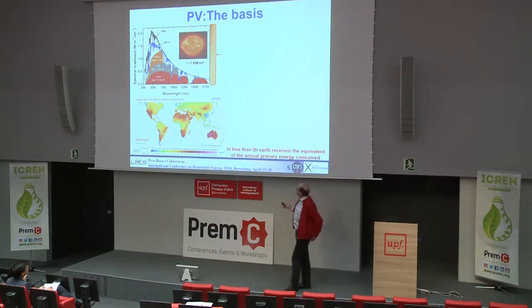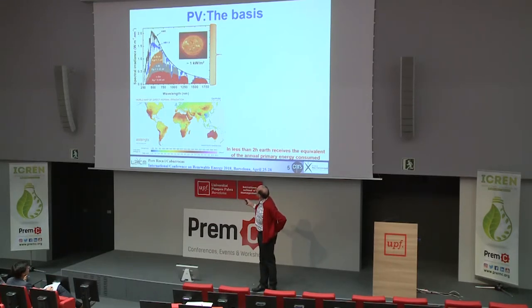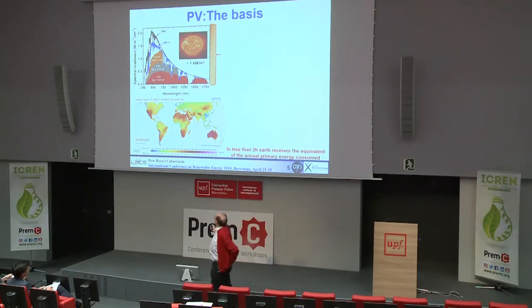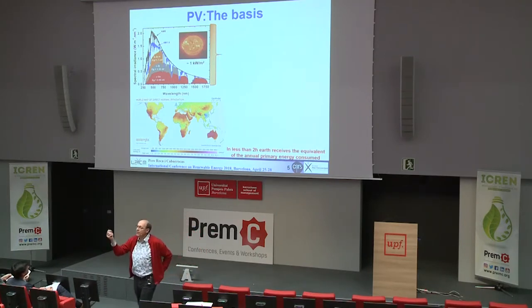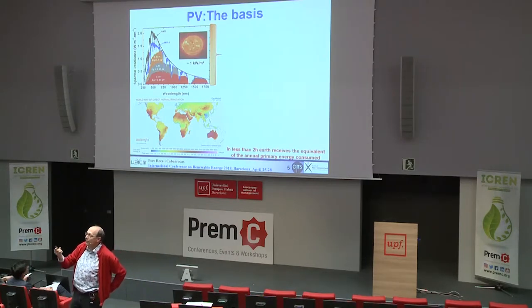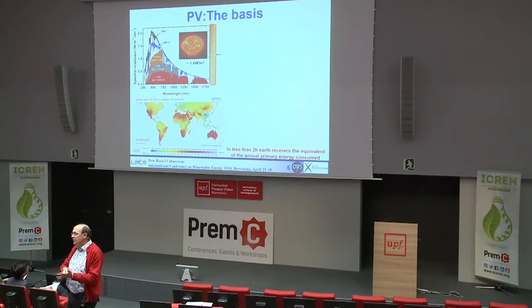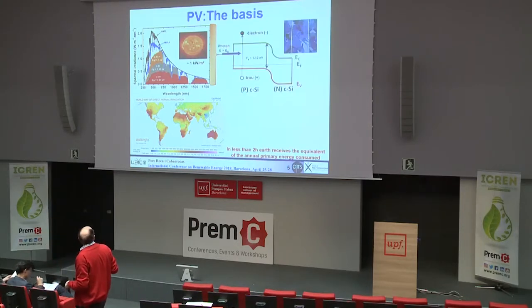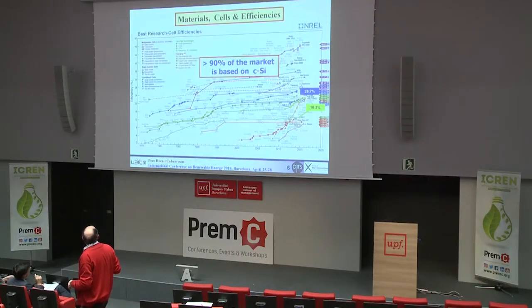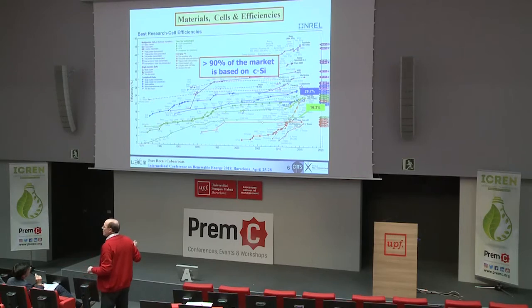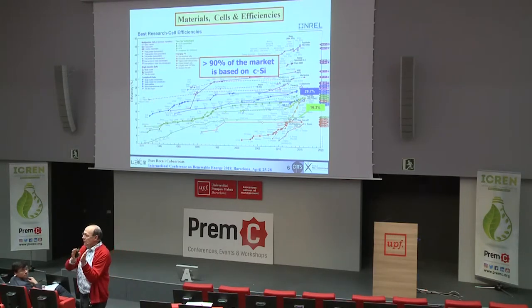If you take a semiconductor, crystalline silicon, with its gap at 1,000 nanometers, all these photons are not absorbed, so you have already 30% of the energy lost by transmission. And the high energy photons are absorbed in crystalline silicon, but for photons which have 5 eV, you will only recover 1 over 5. So these are thermalization losses and transmission losses, single junction, 29, 30, depending on the material. And that's why you have to do this 46%, when you combine 1, 2, 3, 4 cells and minimize the thermalization for each cell.